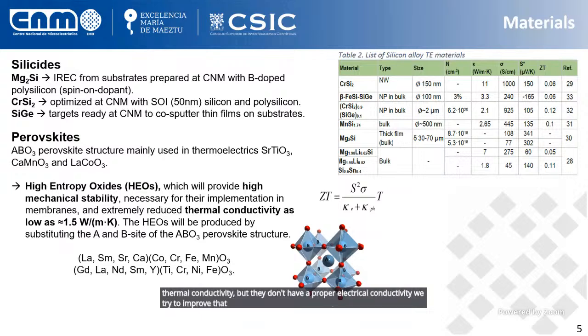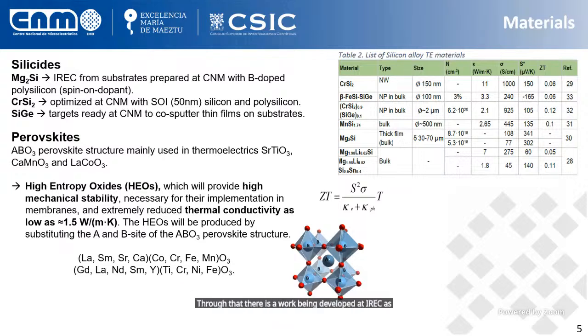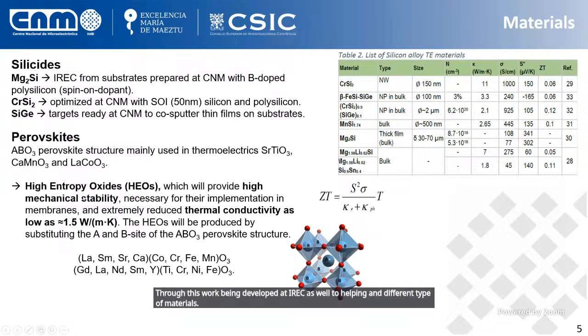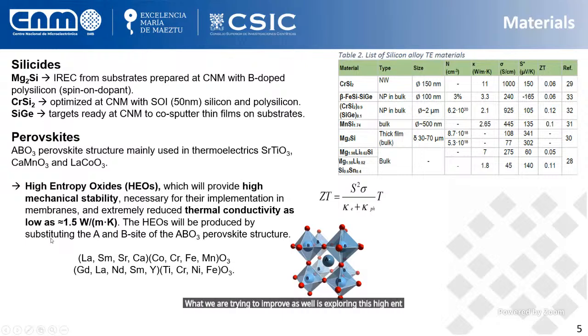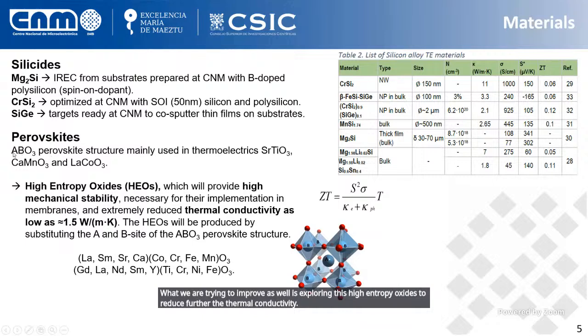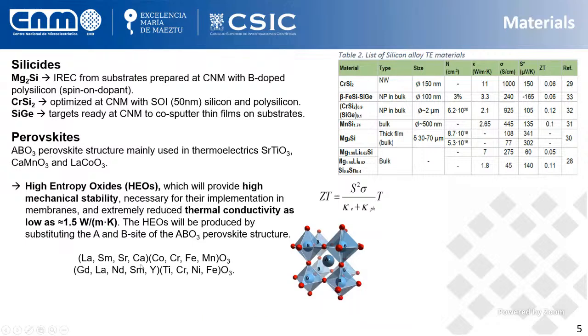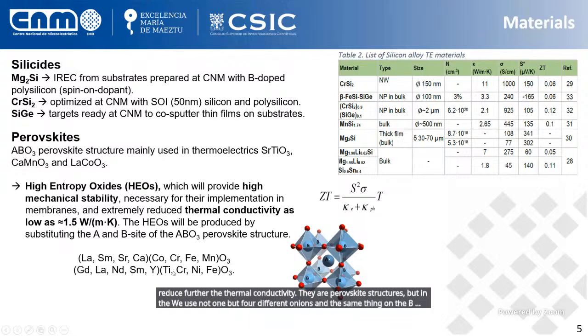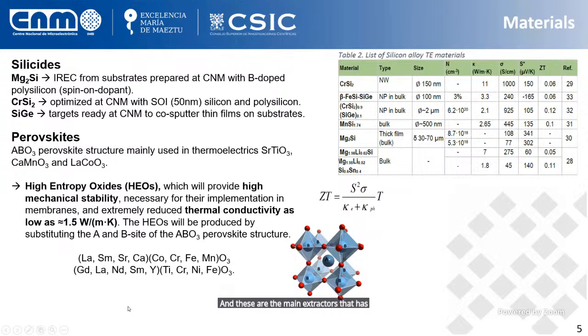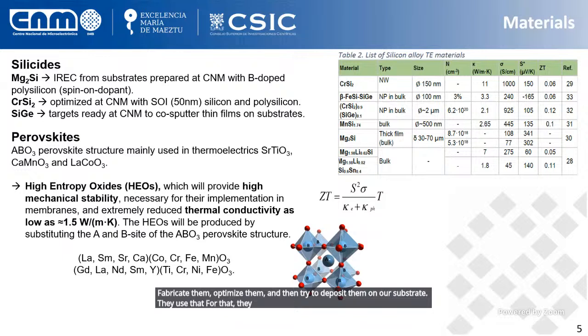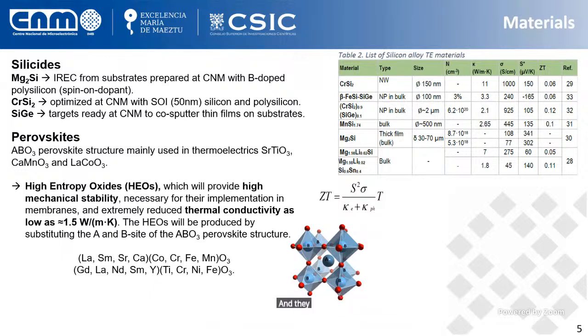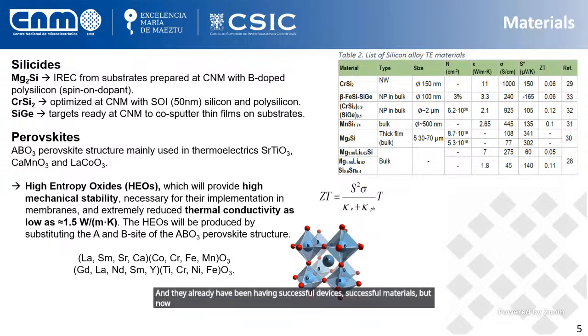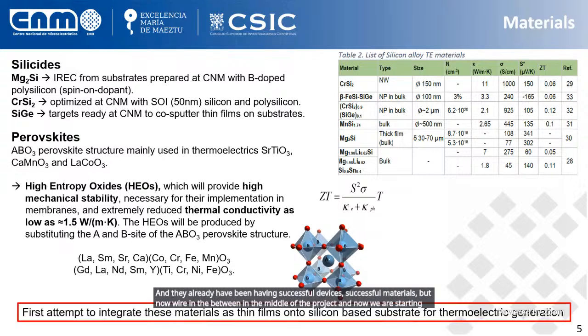We try to improve that through work being developed at IREC as well, through doping and different types of materials. What we are trying to improve as well is exploring these high entropy oxides to reduce further the thermal conductivity. They are perovskite structures, but in the A site we use not 1 but 4 different cations, and the same thing on the B side. And these are the main structures that are being tested right now at IREC to fabricate them, optimize them, and then try to deposit them on our substrate. They use a PLD machine for that, and they already have been having successful devices, successful materials. But now we are in the middle of the project, and we are starting to grow them on our substrate. And I guess, as I mentioned, this project is the first attempt to integrate these complex materials as thin films onto these silicon-based substrates for thermoelectric generation.